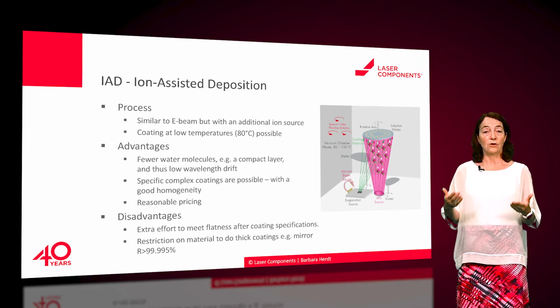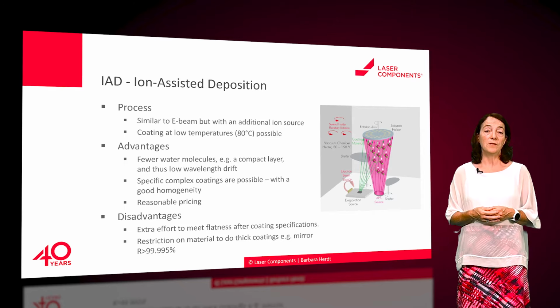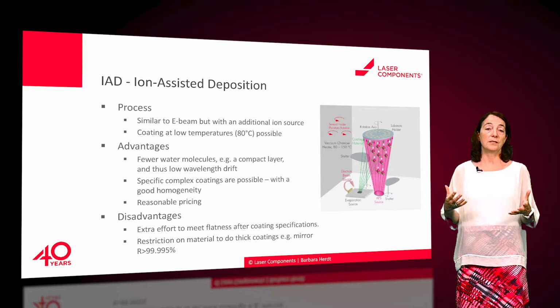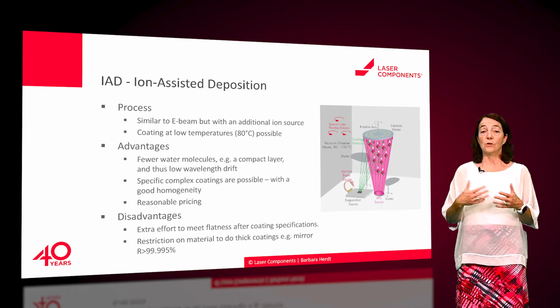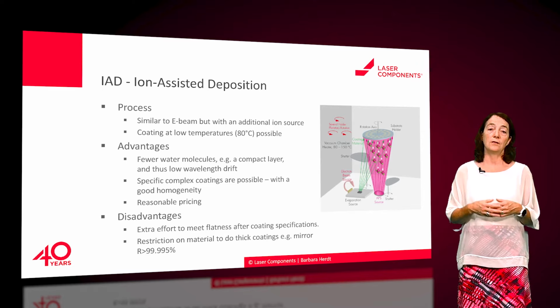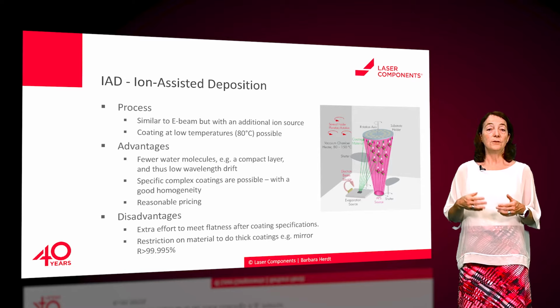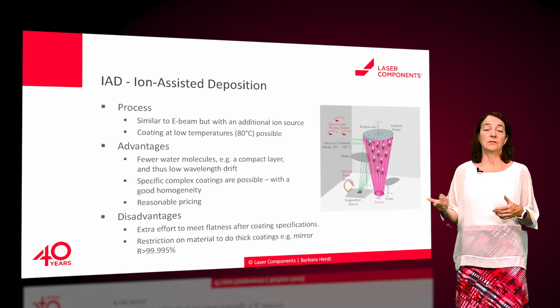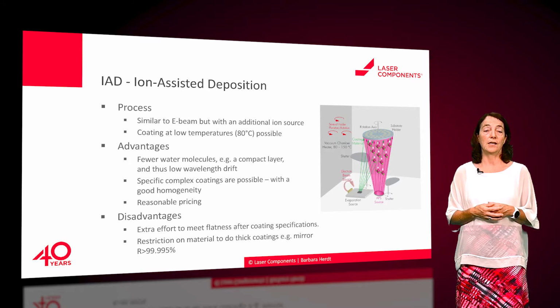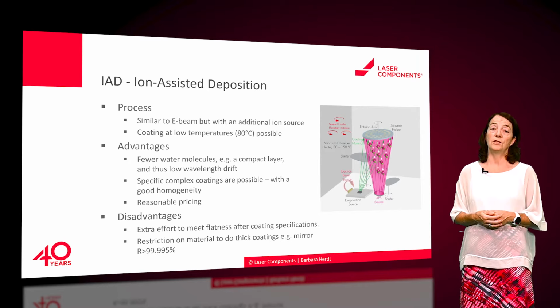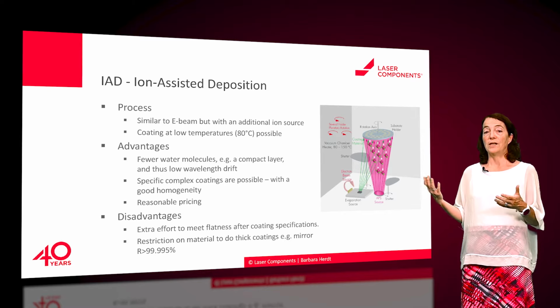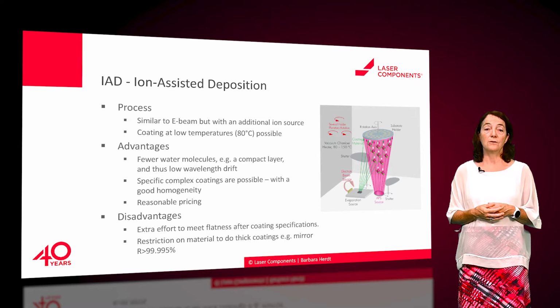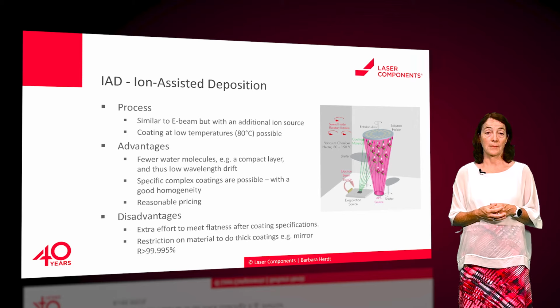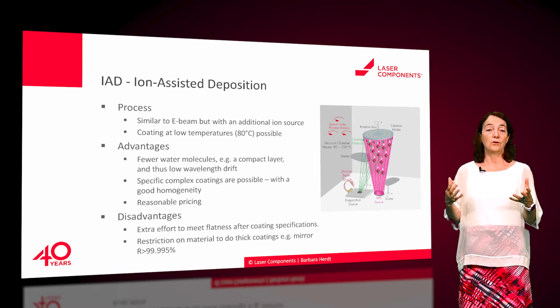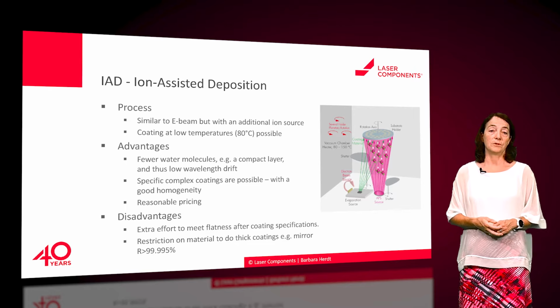With this technology, a much denser coating than with E-beam can be reached. This is one of the big advantages. There is no wavelength drift in vacuum application or temperature changes. Also, the online monitoring during the coating process allows more complex coating specifications with a good homogeneity over the chamber. Our chamber has a homogeneity better than 1% of a diameter of 15 inch. This allows a reasonable pricing as a large area can be used and coating on large optics is possible.